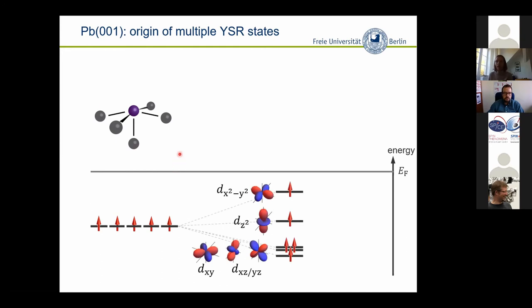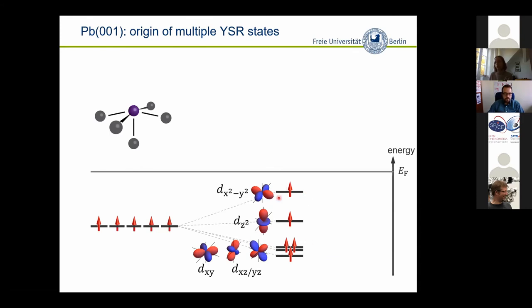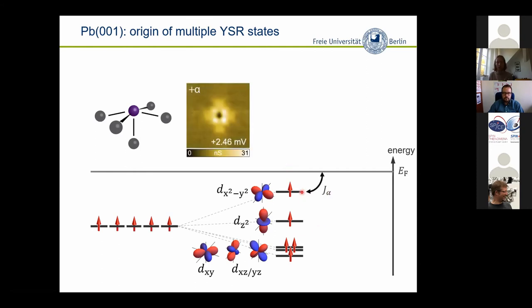Starting with manganese — five electrons in the d shells, in principle a spin-5/2 system — you remove these degeneracies by imposing the crystal field. Using simple crystal field arguments: the orbitals pointing towards the bonding axis are pushed up most in energy by electrostatic reasons, so the d(x²-y²) orbital is pushed up most. Then comes the d(z²) orbital, and finally the d(xy), d(xz), d(yz) orbitals stay lowest in energy, remaining almost degenerate. The splitting is still low enough that we don't go to a spin crossover — we remain with the occupied levels, which present an exchange scattering potential to the substrate Cooper pair electrons, giving rise to specific symmetries of the scattering potential.